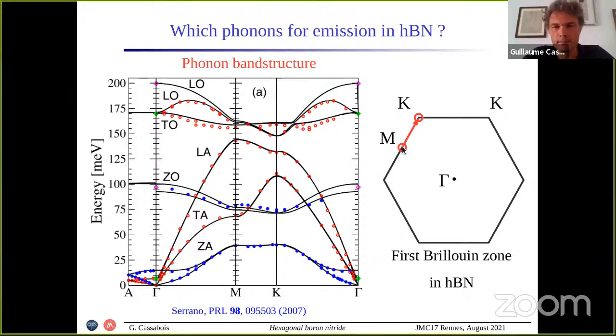It means that the phonons for momentum conservation will have a wave vector which connects the M to the K point. If we translate this to the zone center, with a basic geometric argument, we see that the wave vector of the phonon is exactly half the gamma K line. So in the phonon band structure, one has to look for the phonons that are in the middle of the gamma K line, no longer at the edges of the Brillouin zone as was the case for silicon, diamond, germanium, or any other indirect semiconductors.